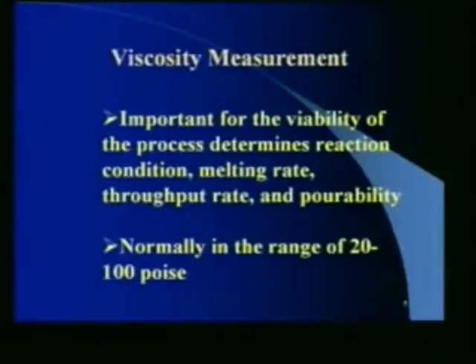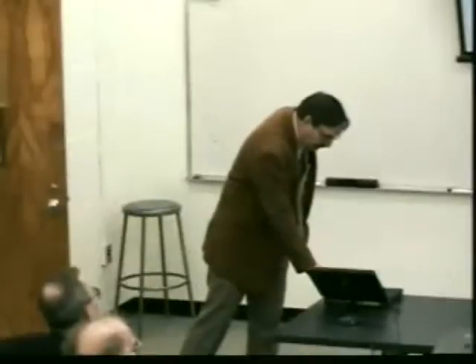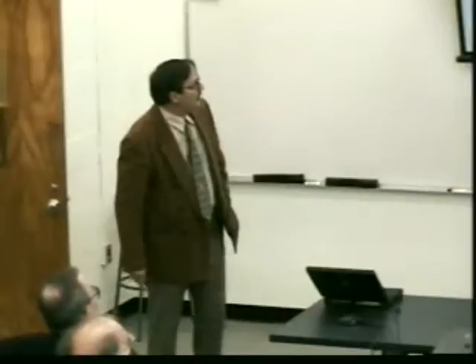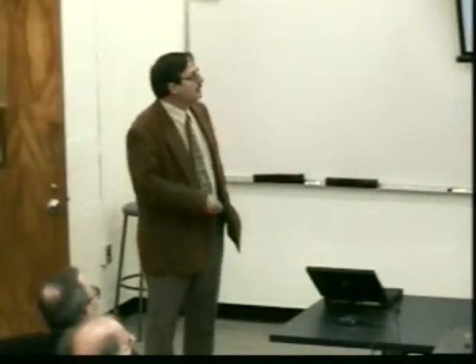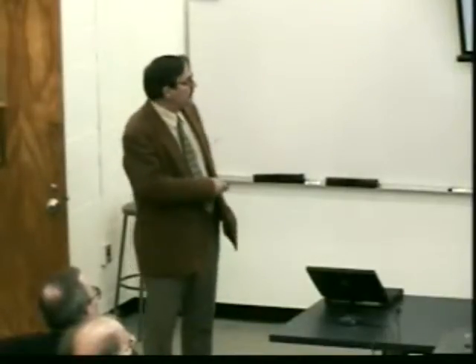Viscosity measurements are, of course, important to the viability of any process that involves a molten phase because it defines reaction conditions, melting rate, throughput, and pourability. And typically, you would like a glass in the viscosity range of 20 to 100 poise. We developed, based on an ASTM standard, a viscosity system. I'll show you a picture.